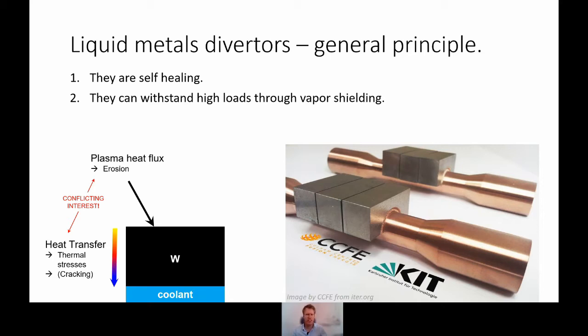But nevertheless, there is an inherent limitation. The problem is that the plasma will erode the tungsten. So to have a long lifetime, you want to start out with a nice thick block, and this will get thinner over time. At the same time, you want to keep the block from melting, and to keep the surface cool, you want to make the block thin. That is how thermal conduction works: a thicker block will get hotter on the top. So from this perspective you want a thin block, not a thick one. This is an inherent conflict of interest that you can only go so far in compromising.